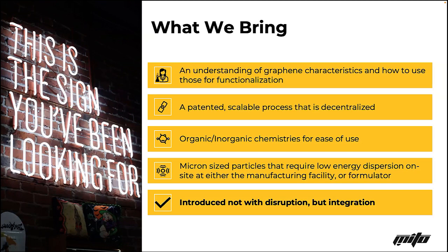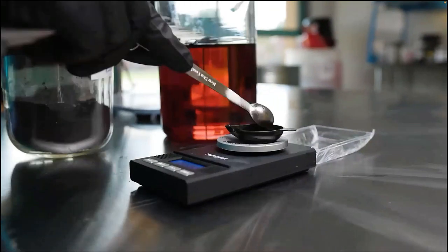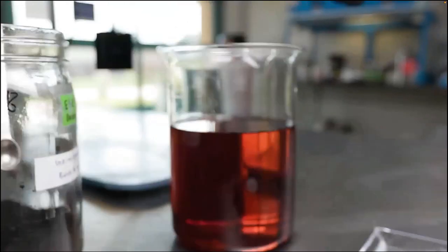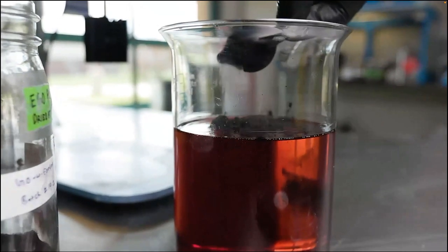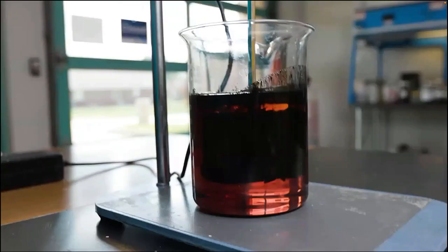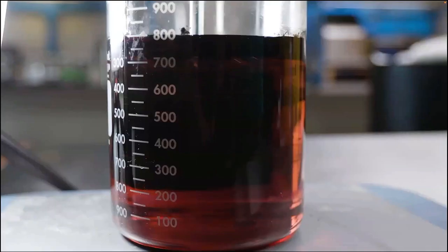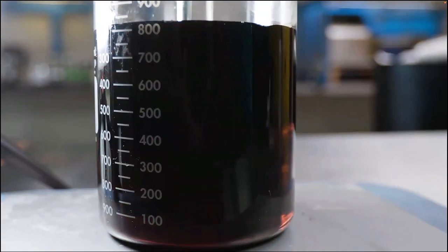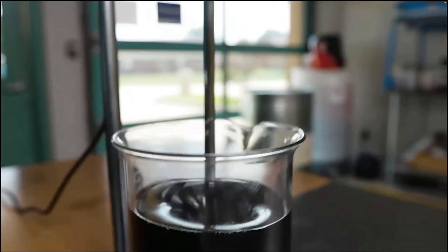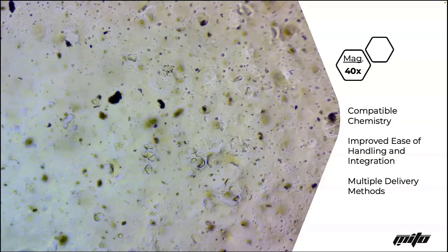So for instance, one of our flagship products is a graphene oxide-based particle, where with a 0.1% by weight mix of the resin, we just weigh it out, put it into the system, and then it's just an easy shear mix where it reactively disperses throughout. We've done this with thermosets and thermoplastics, and when you cast it, what you see under an optical microscope at 40x is that it is dispersed. These black particles are more stacked layers, but they still have that chemical functionality to better increase that surface interaction that you really want from these nanomaterials.